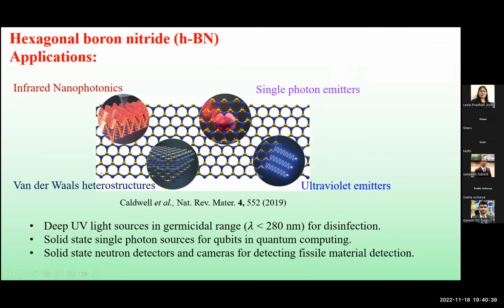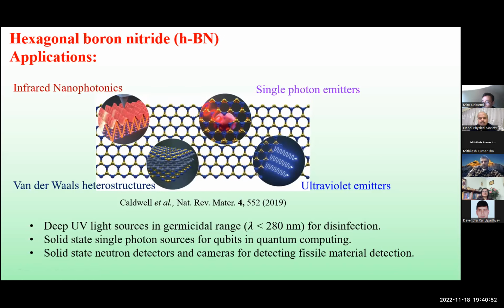It's not only UV emission. Because of the layer structure, this material is also attractive as a 2D material, because those layers are bonded by van der Waals forces, and there is a lot of research going on heterostructures with boron nitride, because graphene and boron nitride have very close lattice constants. Boron nitride could be the substrate for graphene, or there are lots of other materials grown alternately or mixed with them. Those are called heterostructures. There is also some interest in infrared nanophotonics, which is active in the infrared region. Recently, another application is the single photon emitter.